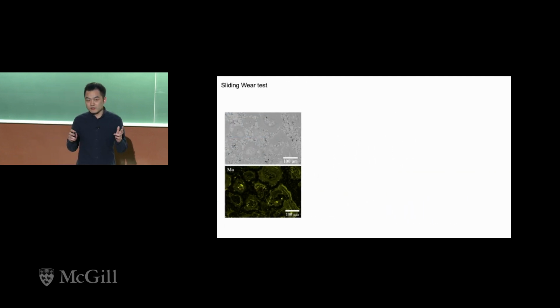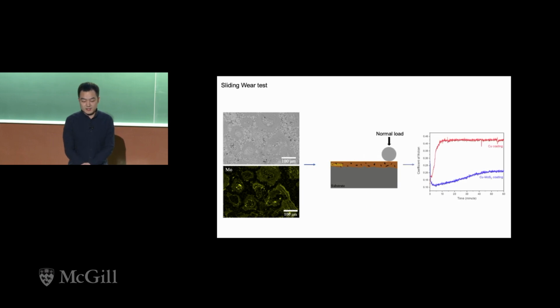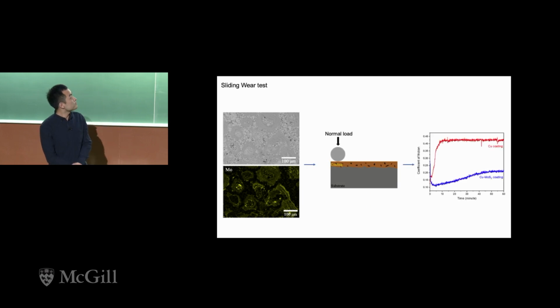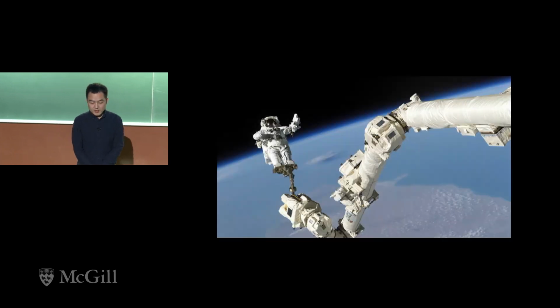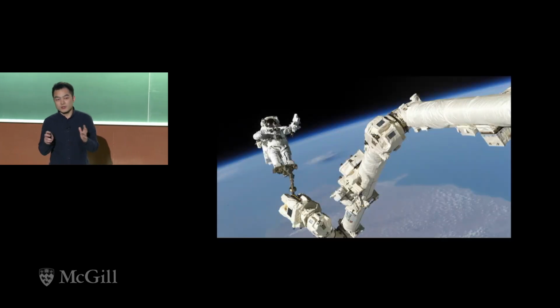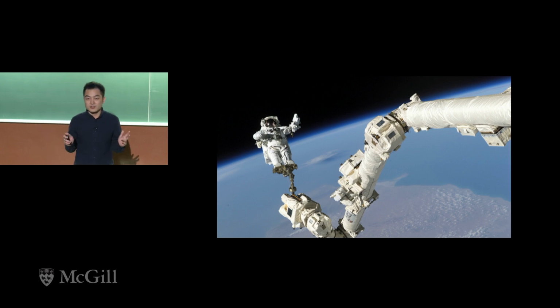We tested its friction performance and found that its coefficient of friction stays steady after around 40 minutes, and its steady coefficient of friction reduced around a half compared to the pure copper coating. In future, we want to produce some coatings with much lower friction, and hope they can help the spacecraft work for a longer time and more efficiently.